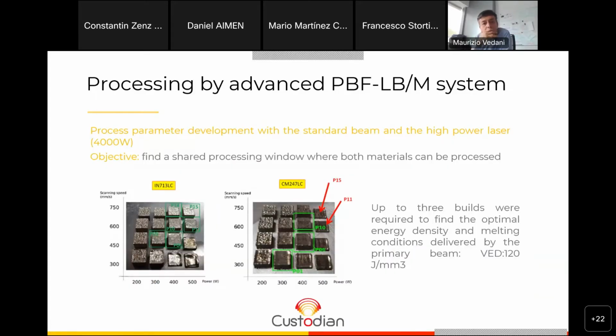So, in order to get feedback about which conditions are required for processing these two nickel alloys, we mapped the processing window for both alloys with the standard beam, with the Gaussian distribution beam, just to make sure that we can produce parts using very similar conditions and to give some feedback to the simulation as well. So we could conclude that a volume energy density of 120 joules per cubic millimeter was required, and that both alloys can be processed under very similar conditions, because in the end, as Mauricio presented, both of them present very similar chemical composition, right? Mauricio, can you skip to the next slides?